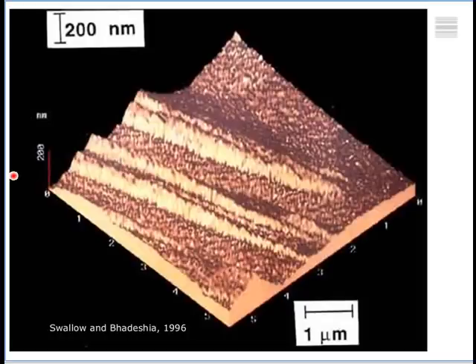And here it is. This is an atomic force microscope image of a crystal of austenite which was transformed to bainite. And you can see that there are huge deformations here. These deformations are physical deformations which cause a lot of elastic strain energy. So that elastic strain energy is stored inside the material. It's very large. If you store that inside the material, then you do not dissipate, you do not create heat which needs to be dissipated. So these transformations have very, very little recalescence as we had in the normal thermomechanical processing. So this is a good way, to exploit displacive transformations to store energy. This is actually bainite here, which has caused these shear deformations.